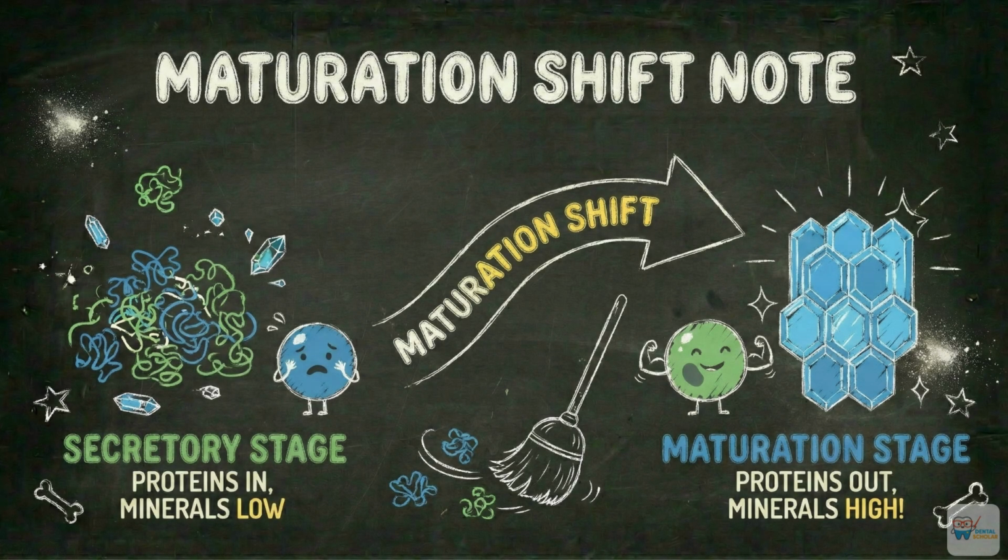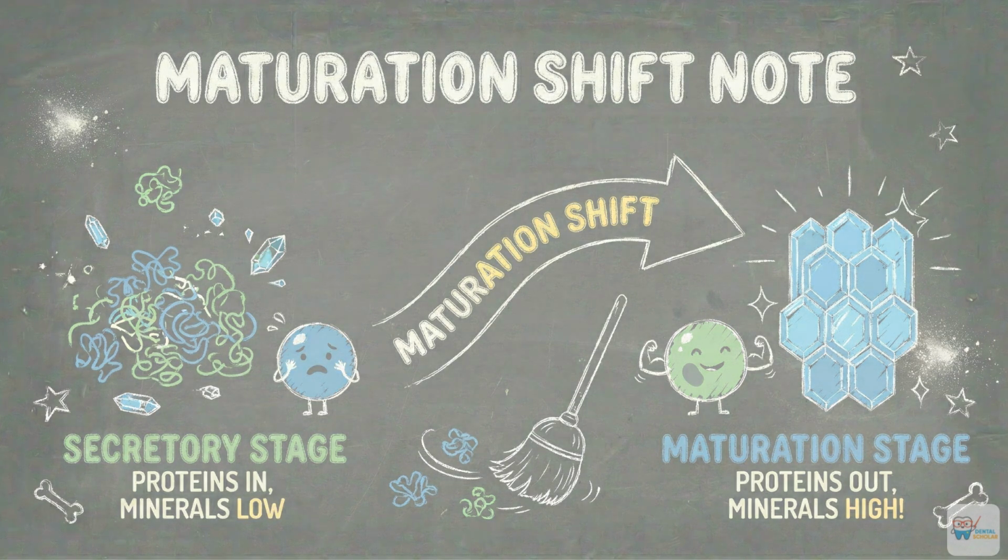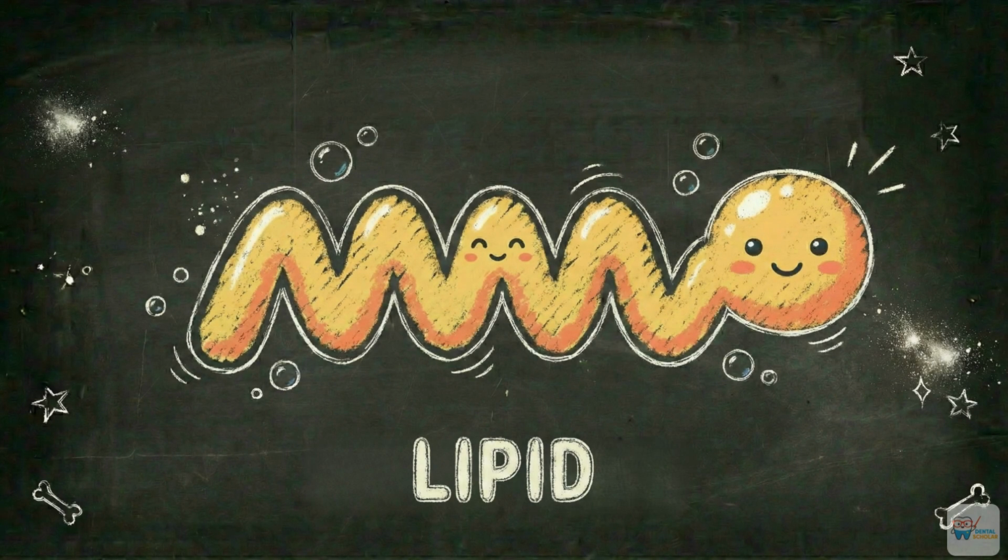As the enamel matures, these proteins are removed to allow complete mineralization. Amelogenins are removed more efficiently. That's why in mature enamel, amelogenins drop from 90% to 10% and non-amelogenins form the 90% of the protein in the mature enamel. Disturbance at this stage, when the proteins are being removed, leads to hypomaturation defects of enamel. Trace amounts of lipids may also be present, which may be remnants of ameloblast cell membranes after their programmed degeneration.